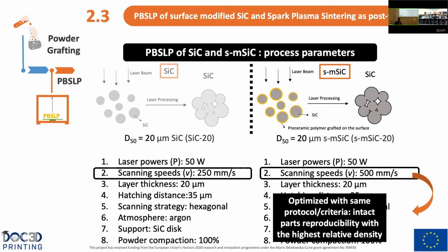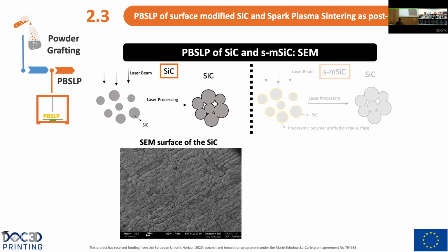Why? Because actually here we were following the same protocol criteria to optimize the parameters. And we observed that by using this scanning speed, instead of this one, for example, we were reaching parts with highest reproducibility and highest relative density. In numerical values, actually, 65% of relative density versus 71% of relative density. So actually, regarding the microstructure of the silicon carbide after the process, again, we can observe a rough surface, no clusters of particles, no melting, no specific pattern defects.